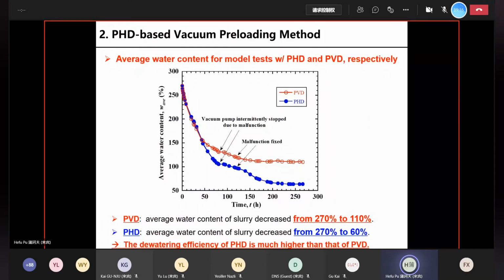We'll also look at the average water content for the model tests with PhD and with PVD respectively. We can see that for the PVD, which is the red curve, the average water content of a slurry decreased from initially 270% to eventually 110%. And for the PhD, which is the blue curve, the decrease of water content is more significant. The final water content is only 60%, which is roughly about 1/2 of that for the PVD. So we can see that the dewatering efficiency of PhD is much higher than that of PVD.